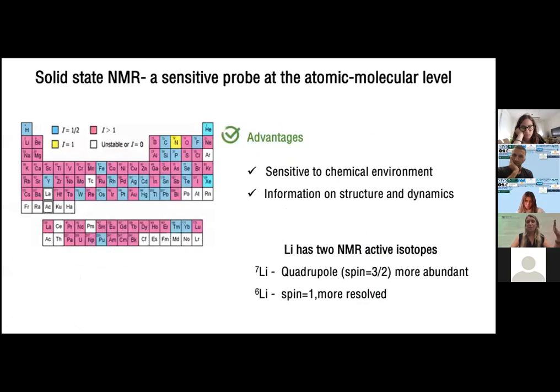So solid state NMR is an excellent analytic tool to study materials. In principle, you can detect most of the elements in the periodic table highlighted in color. It's very sensitive to chemical environment. It can give you rich information about structure and you can follow dynamics. And especially it's very useful in the research on lithium batteries because lithium has two NMR active isotopes, lithium-7, which is more abundant, and lithium-6, which has much higher resolution.